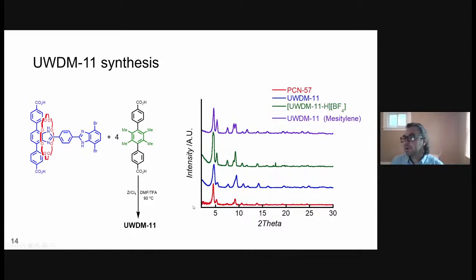One of the nice things about this material, as we can see from PXRD, is that we can activate it, we can add acid to it, we can then add new guest molecules to it, and we don't see any structural changes or loss of crystallinity. So this is a very nice, robust system that we can do a lot of things with that are going to affect the dynamics in the solid state. And once again, this is why we're working with these nice, robust zirconium type MOFs.